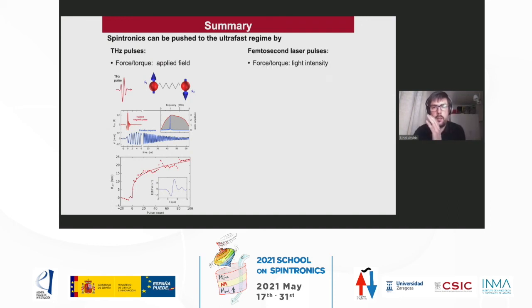And the second part has been about femtosecond laser pulses, the optical pulses. In this case, the force or torque is the light intensity. This optical pulse energy is absorbed by the electrons, the electrons are heated, and this energy is transferred to the lattice and to the spins. I gave you an example which is paradigmatic because it was nickel, which was the first magnetic material showing this sub-picosecond response to an optical pulse.